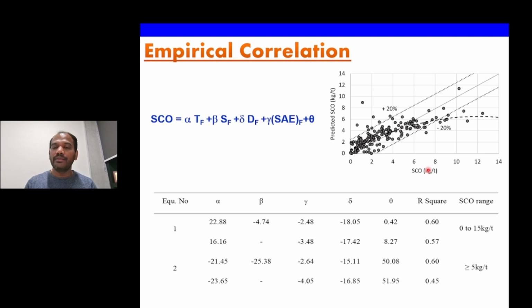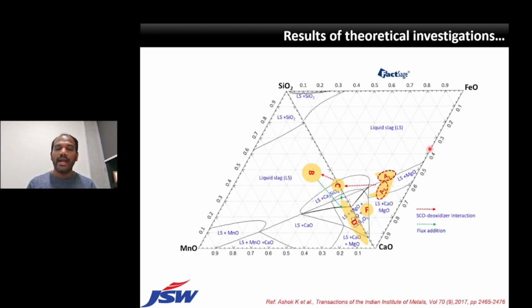And the slag carryover predicted has been compared with an empirical relation with the FactSage estimated slag carryover, with the coefficients given here, and you can see till 5 kilogram per ton the prediction success is somewhat okay. However, beyond 5 kilogram per ton the prediction success is very poor. And this is the slag path, how it actually traveled.